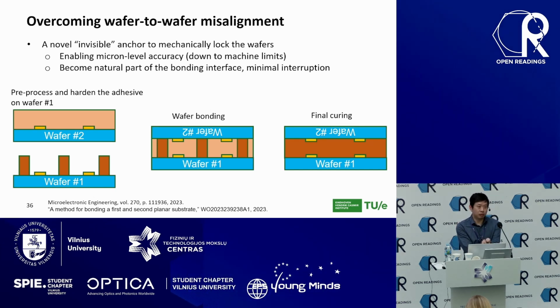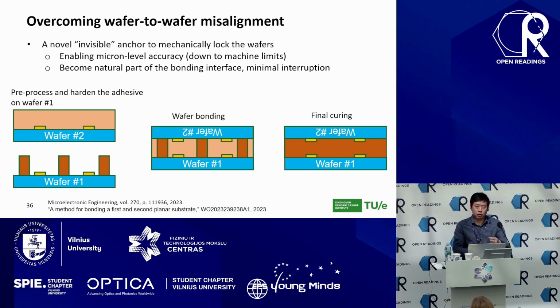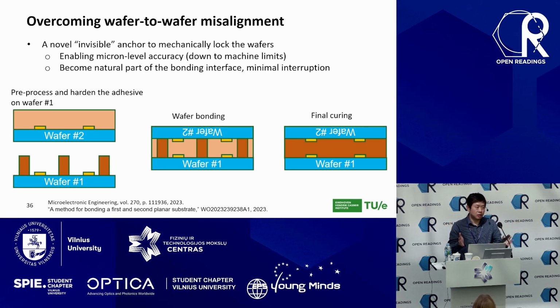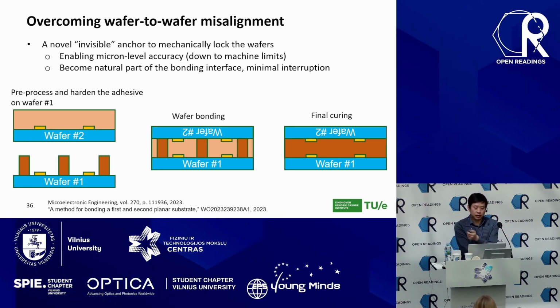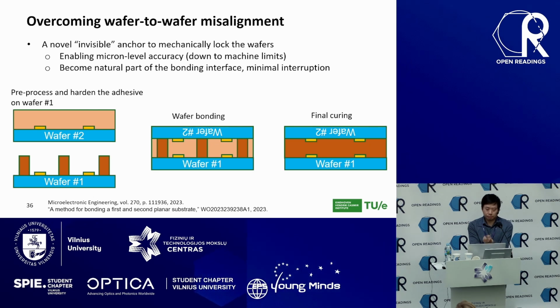Then we perform the wafer bonding. And you can imagine that those hardened pillars penetrate through the liquid and reach into the surface of the top wafer. And using the friction, we can achieve a mechanical locking. And the magic happens when we do a thermal treatment to cure the entire system. Then the bonding interface becomes an entire, completely hard cured polymer. So the anchors we created before become part of the bonding interface. And this is the trick we play.